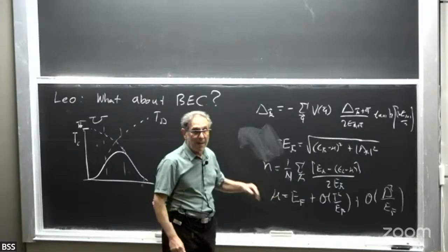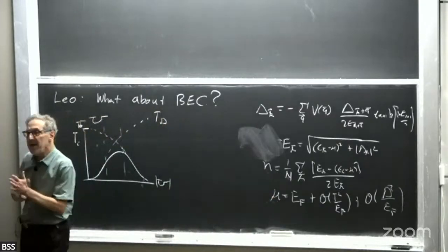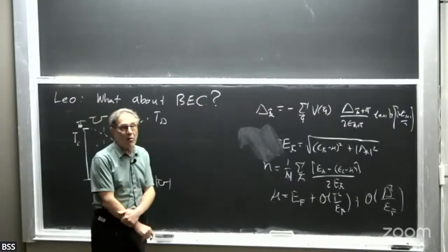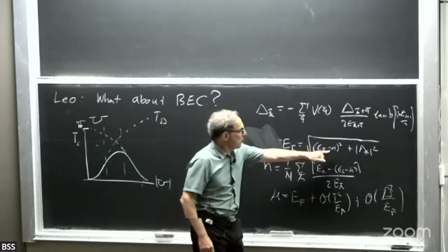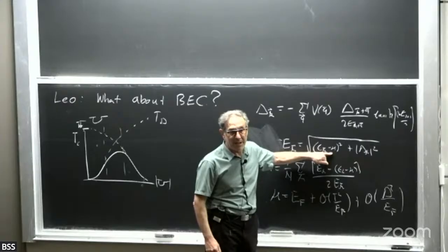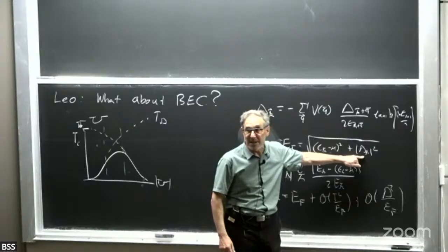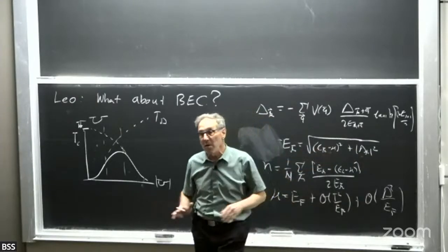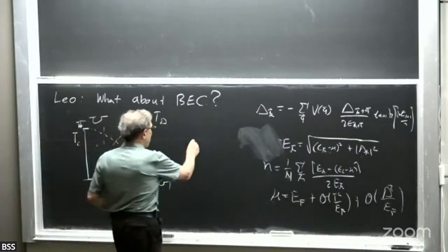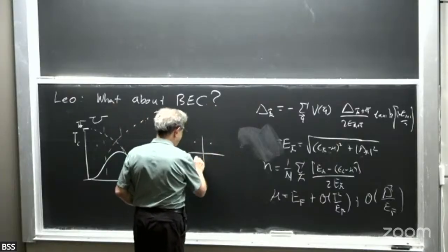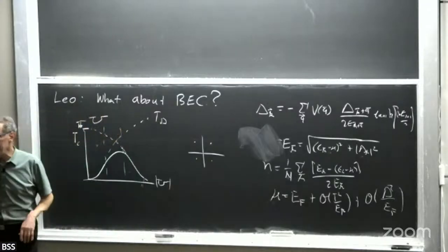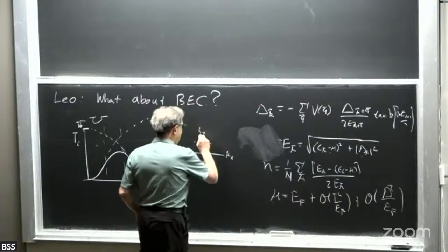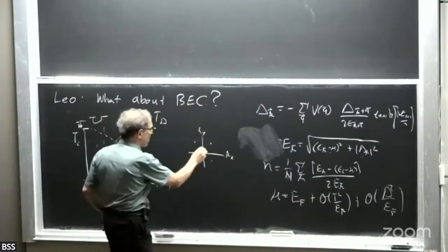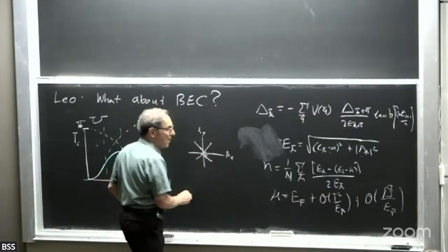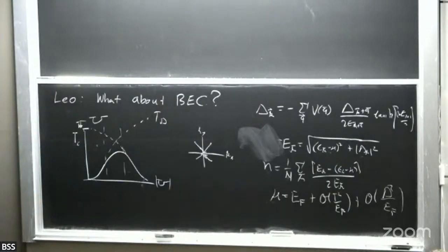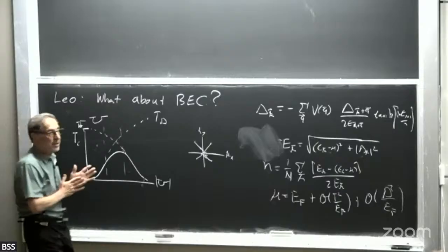What about in the cuprates? Well, first, in the cuprates, because they're a d-wave superconductor, there's the BCS to BEC crossover. If mu is below the band bottom, then this quantity never vanishes. So it doesn't matter that delta vanishes along lines in k space; since this thing is always positive, there are no nodal quasiparticles. So if I just artificially turned up the interaction in a d-wave superconductor, these nodes in k space would move together. And then at the BEC to BCS crossover, when the chemical potential goes below the band, there would be a Lifshitz transition and you would go to a nodeless superconductor.